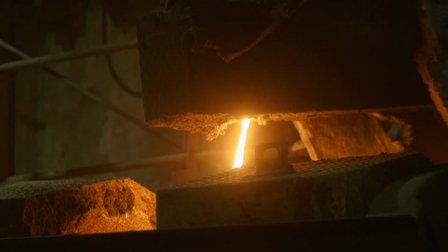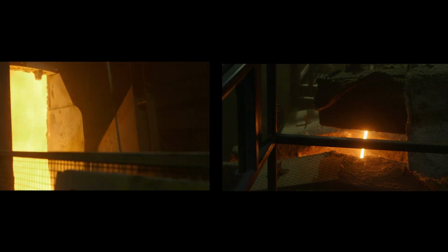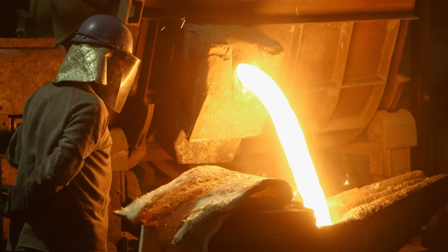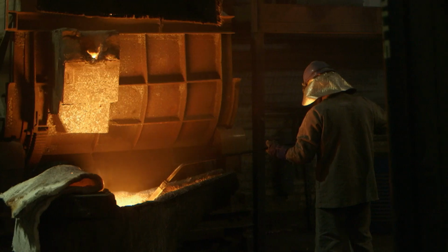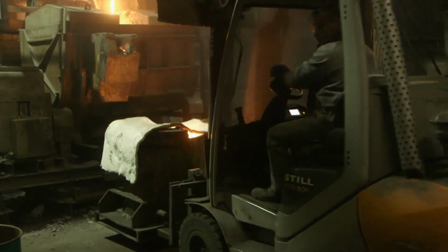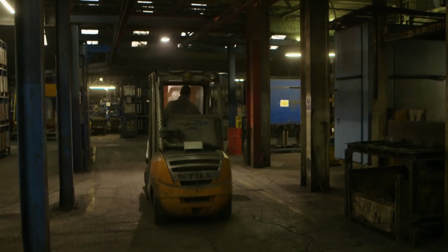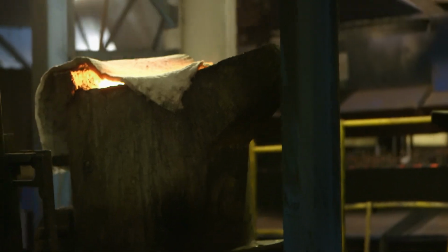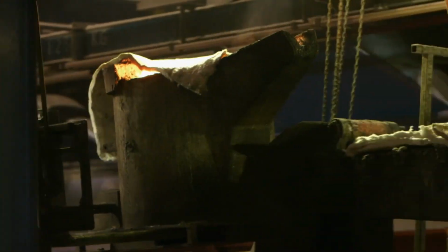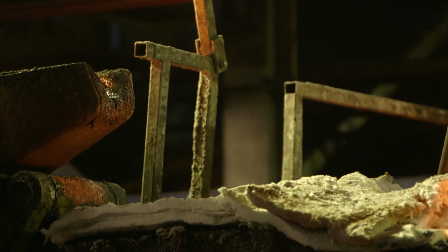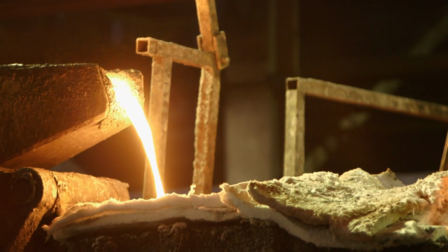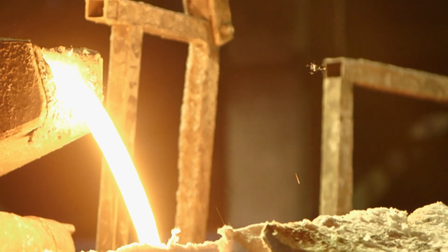and melted. That's the first stage in the process, which is key to us to ensure that the consistency and the chemical attributes of the product are right. The furnace can melt 5 tons of cast iron per hour. Once melted, the molten iron is taken to 2 of the moulding lines in a container or large ladle. The molten iron inside is still at a blistering temperature of 1400 degrees Celsius.